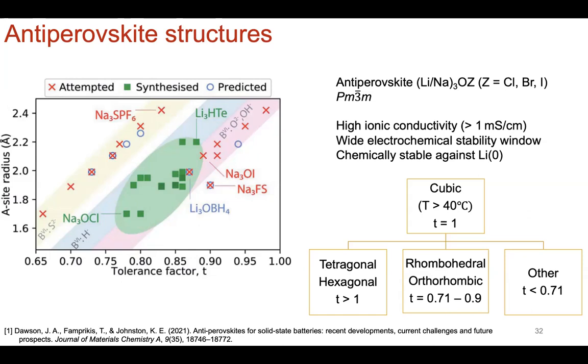And it's for the reason, well, one, the phase transformations occur at relatively low temperature. And in solid electrolytes, right, what you really want to track is the ionic conductivity as a function of inverse temperature. But you want data that you can fit an Arrhenius relationship within a temperature range. If you have a phase transformation, you now have a different Arrhenius type relationship. So that's not the end all be all, but if your material is undergoing phase transformation at relatively low temperatures, you have an issue with fabrication.